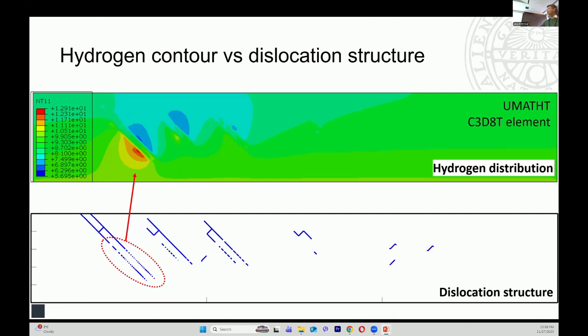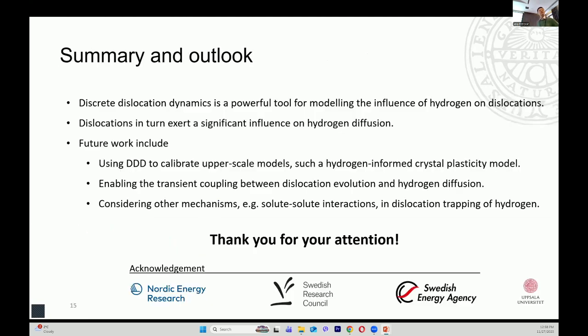And further, if you compare the non-uniform distribution profile with the discrete dislocation structure I showed earlier, and this is a 2D view, you can see that really it corresponds to the locally accumulated dislocation pile-ups. So with this approach, we show the possibility of using DDD to directly simulate hydrogen diffusion and redistribution. And in the future, we could use this approach to calibrate the dislocation density and dislocation binding energy, and we can compare it to the experimental values. And further, this provides a way to really link hydrogen redistribution to the microstructure. So this could be a potentially promising approach, I believe.